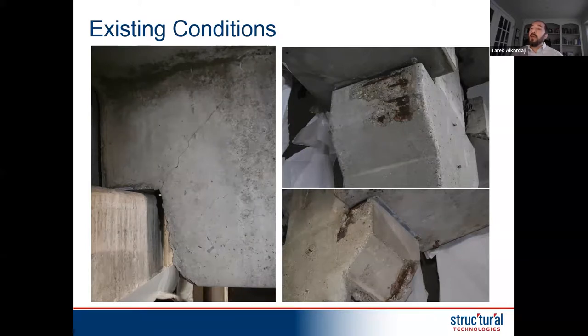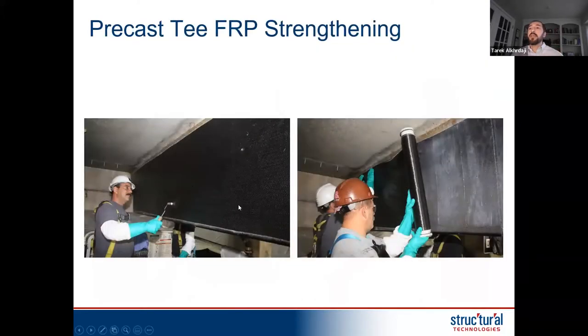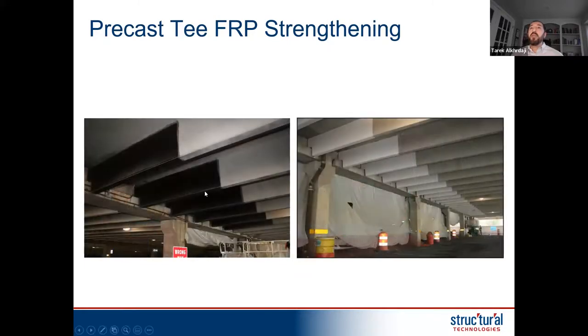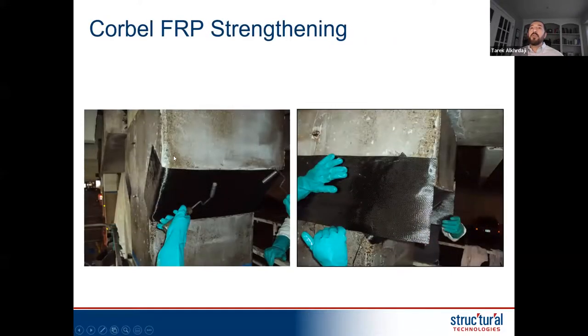So once that happened, the authority came up with a program to rehabilitate this parking garage, come up with a solution, including fixing all the corroded concretes, injecting all the cracks, wrapping with FRP, adding shear capacity based on some assumptions. So here you can see adding the shear capacity for the elements, wrapping it with FRP. You can see the end after they're wrapped with FRP and coated for long-term protection. And also the column corbels, here you can see this one actually after it was repaired and injected with epoxy, the FRP been tailored around it with proper overlap to ensure continuity.